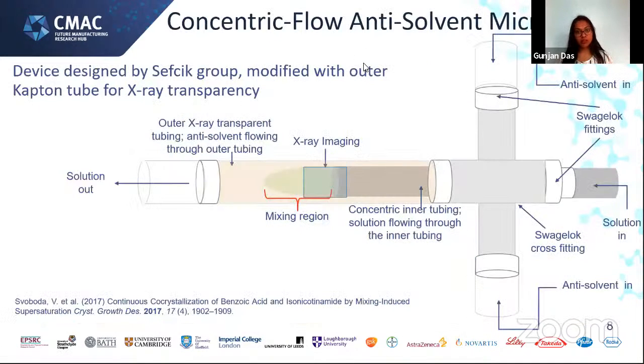Speaking of the crystallizer, we have been using a concentric flow antisolvent microreactor, which was initially designed by the Sefcik group. And what we have done is we have modified it with an outer Kapton tube for X-ray transparency. We had the solution with the API, glycine or lovastatin in the case that we have studied, flowing through the inner tubing. And what we had flowing through the outer tubing was antisolvent, which would force the crystallization to take place. We have also taken X-ray imaging at the end of the inner concentric tubing and the beginning of the mixing region. The resulting slurry solution was collected later on to collect the crystals and perform some tomography.